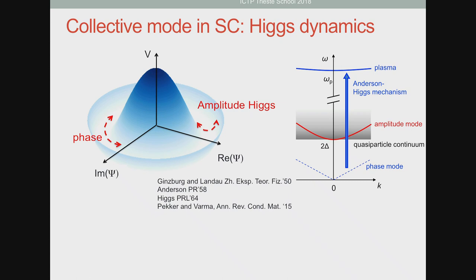So as you have seen in the first lectures, you can describe your superconductor in terms of a Landau functional. And this is very general, right? So you have this Mexican hat potential. And once you look at this Mexican hat potential, the ground state is sitting at the bottom here. And you can have, from a very general point of view, two kinds of collective excitation, one that will involve the phase of the superconducting order parameter, and the other one that will involve its amplitude.